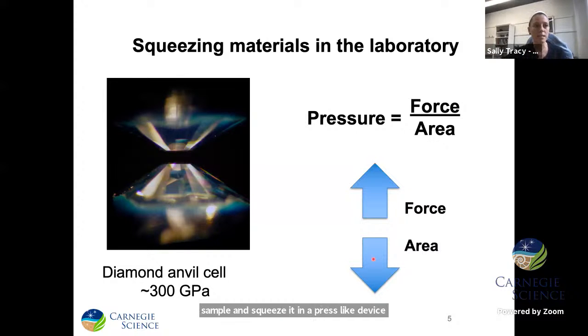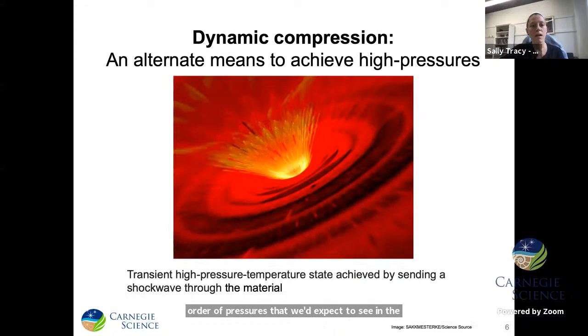And so the current state of the art for this type of measurement uses a device known as a diamond anvil cell, which is a technique that was pioneered here at Carnegie in the last 50 years or so. And with this instrument, we squeeze a sample between the tips of 2 gem quality diamonds, where the small area and the high strength of diamond allow us to generate very high pressures, on the order of pressures that we'd expect to see in the center of the Earth.